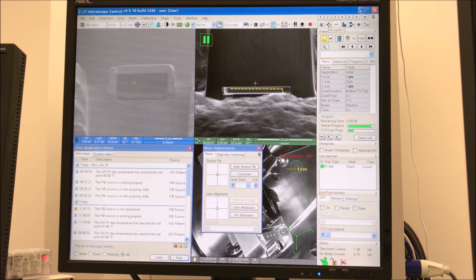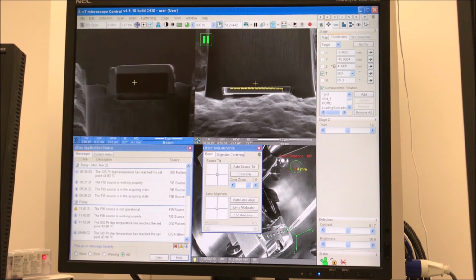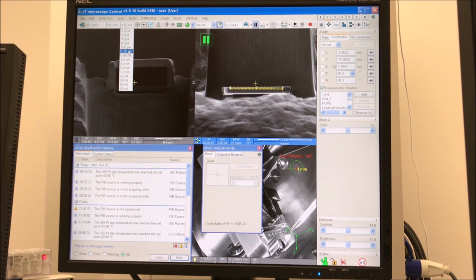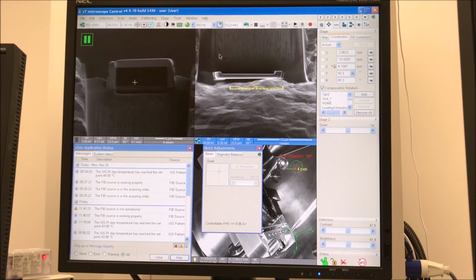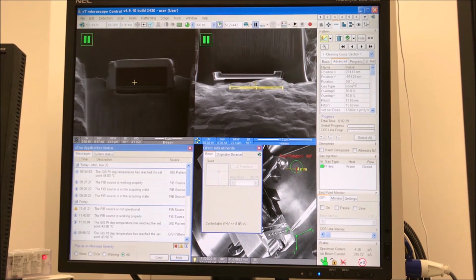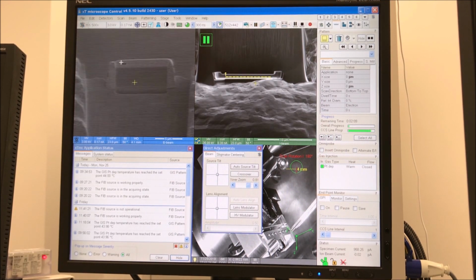This is sped up a little bit. Once this is done, I'm going to tilt minus 1 degree away from incidence. I'm going to drop my ion beam current down to 0.3 nanoamps. Rotate the pattern so it's 0 degrees. It was previously 180. I don't think I mentioned that, but it's now 0 degrees. I'm going to execute it from the bottom, and I'm actually going to drop the X dimension down a micron to a micron and a half.